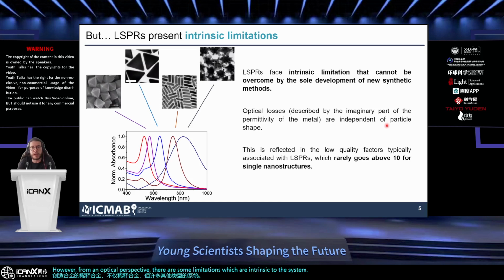which is related to the fact that these nanoparticles present very big optical losses, which basically translate into resonances which are pretty wide. We can express these optical losses by looking at the efficiency of the resonance, the full width at half maximum over the energy, which is expressed as a quality factor. To give you a ballpark, generally colloidal systems don't go above 10 in terms of quality factor of their localized surface plasmon resonances. And so there has been a huge push from the community to try to address this problem, to try to access higher quality factor structures.